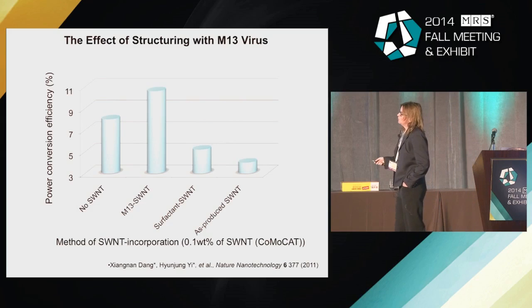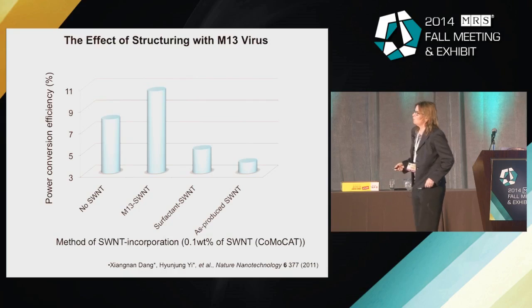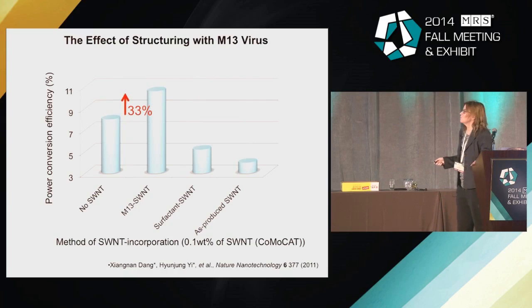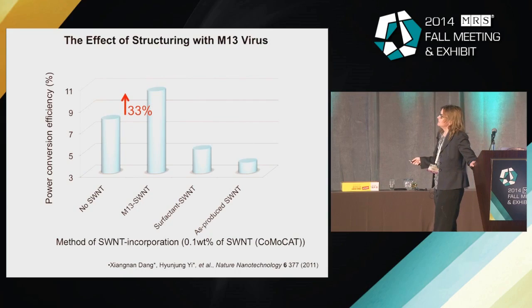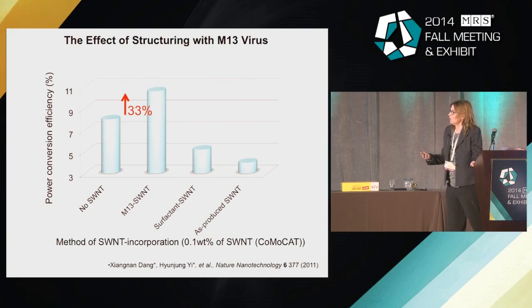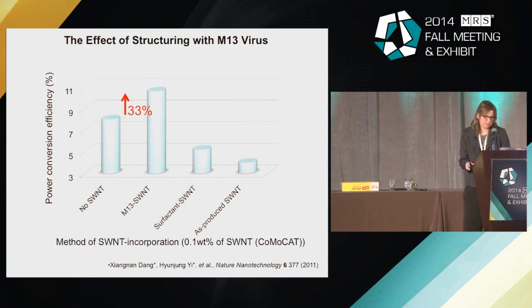And so this is actually our solar efficiency for these dye-sensitized solar cells without CNTs. We were able to get an increase of 33% by adding the CNTs in just a couple of percent incorporation, where they would provide a path for the electrons directly to the current collector. And we compared these to ones that either had surfactant or as-produced CNTs. So the as-produced CNTs would actually clump in the structure without the virus, and it would decrease the efficiency of the solar cell.